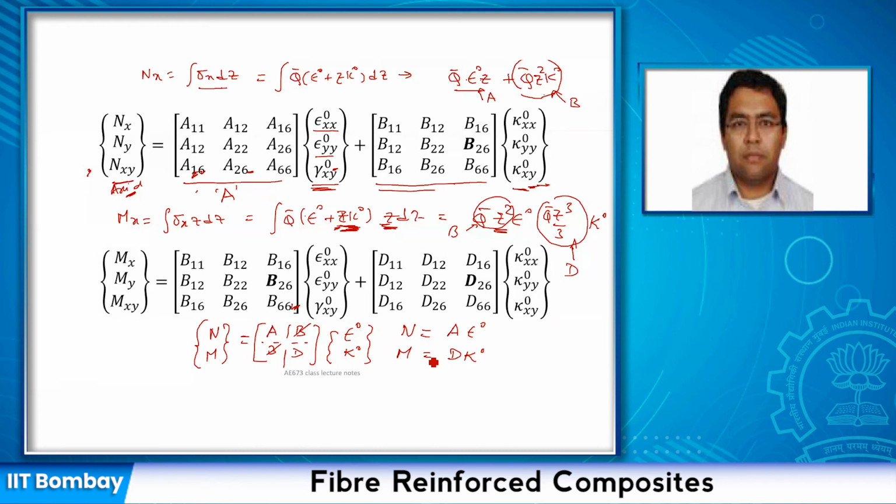But then there are also bad things because of this. If you are making a part where there is a strong B matrix coupling, imagine after curing the part goes through some temperature cycling, because of curing. Now, when the part is taken out of the mold, there could be some warpage to begin with because of this coupling. So there are both advantages and disadvantages.